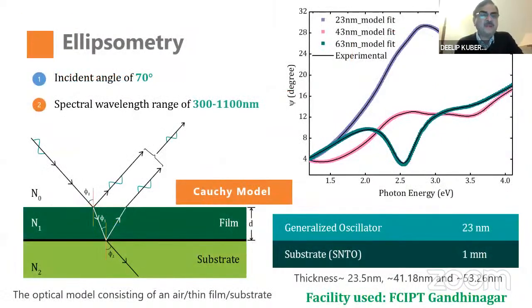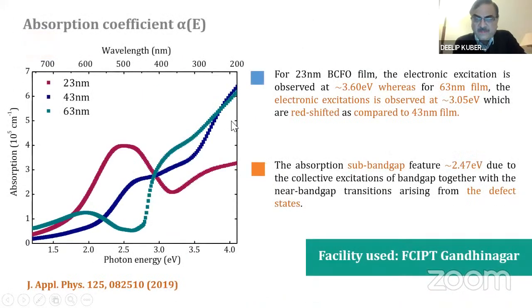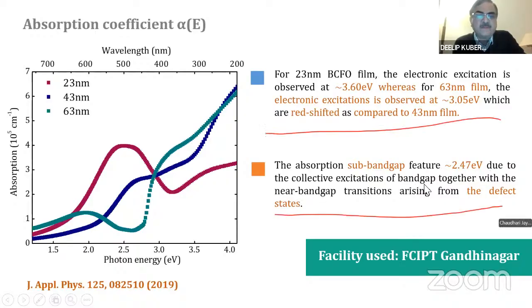And then we did the ellipsometry studies using the FCIPT facilities. Again, two aims. One is to confirm the thickness, for which we used the Cauchy model to fit. And then we found out the sub-band gap features. We have got the absorption sub-band gap features at 2.47 electron volts due to the collective excitations of band gap, and these are arising from the defect states in the material. So this has been already published 2 years before.